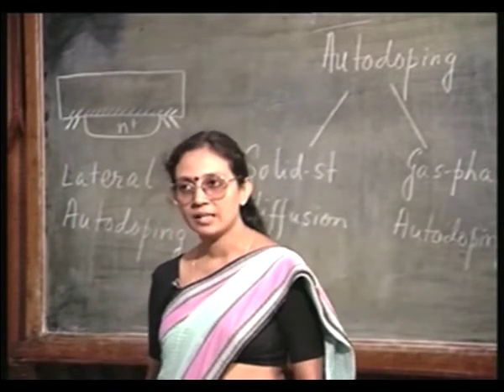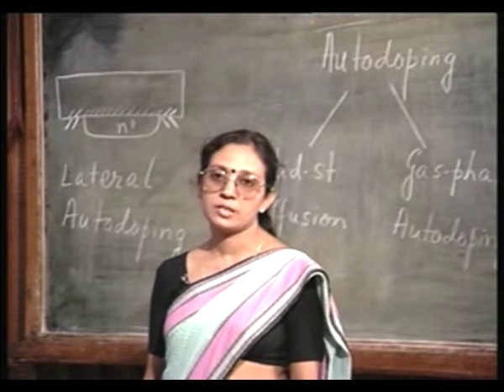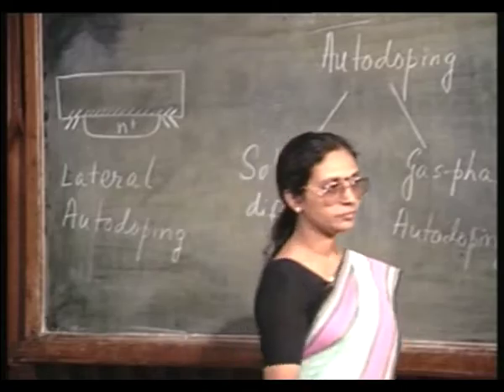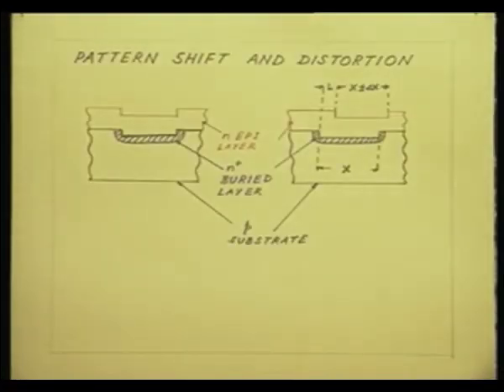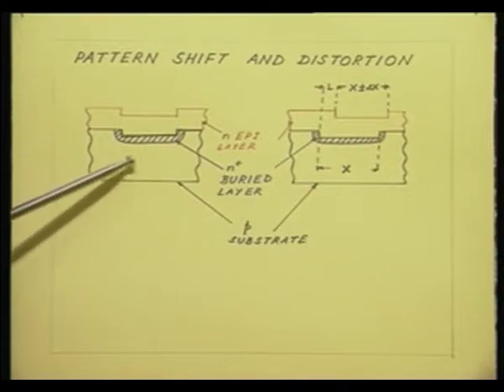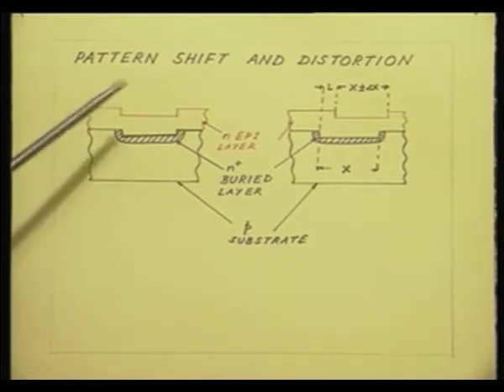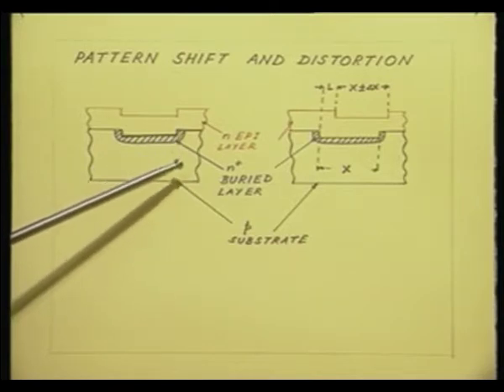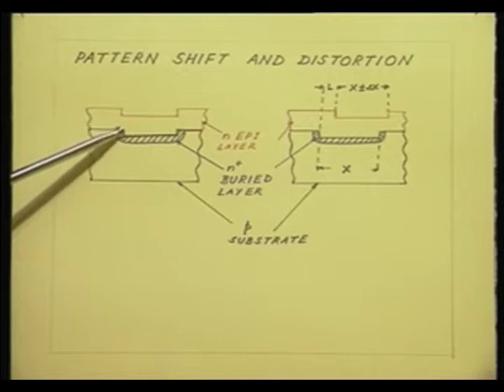Now, there is another interesting aspect associated with epitaxy. You see, normally I would assume that when there is an indentation on the surface, that is a step on the surface, okay, and if I am growing an epitaxial layer, that same step will be transformed into the epitaxial region also. That is, what I expect is something like this. See, what I have drawn here is simply the process steps involved in the bipolar junction transistor fabrication. I started out with the p type substrate, then I have made the N plus buried layer, okay, then I have stripped the oxide, and in doing so I have created a step here. Okay. The step is visible to all of you, you can see the step, right.